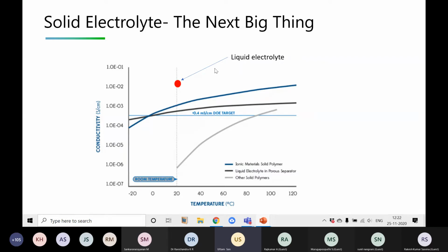So you can see this liquid electrolyte is around 10 to the power minus 2 Siemens per centimeter. Okay. Where for the solid electrolyte, it is significantly low at room temperature. It will improve if the temperature is high.